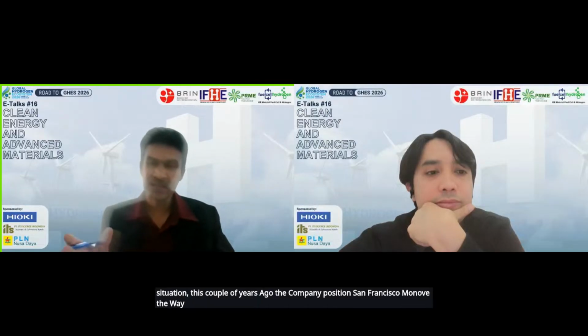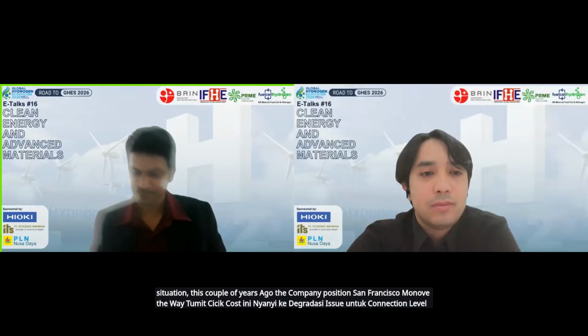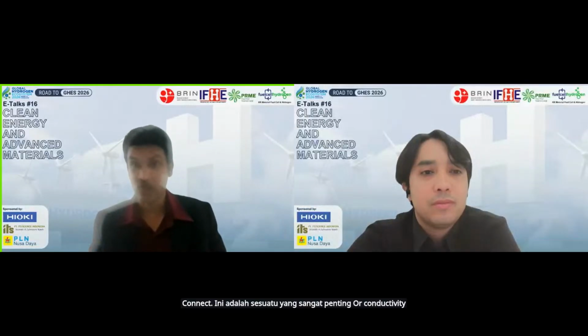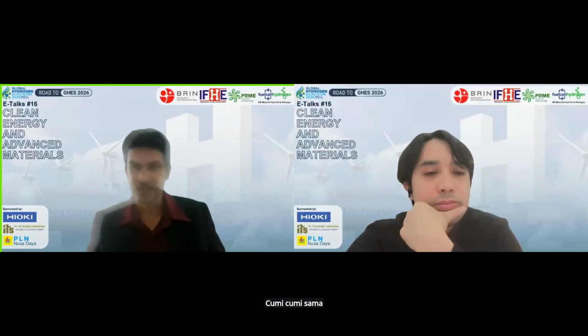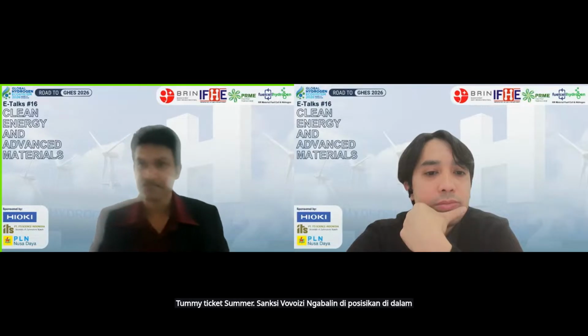Meaning this is a new way to mitigate the nickel coarsening and nickel degradation issue in the conventional electrodes. So one of the issues with these materials is we need to consider the overall conductivity under that condition. So the key reason for the exhaustion is to mitigate some of the chemical issues, the sulfur poisoning, carbon deposition, for long-term stability. Yeah, I hope I answered these questions.